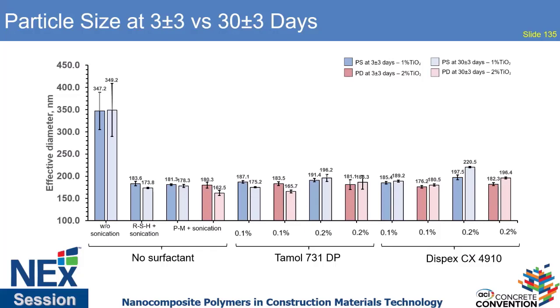However, what is the benefit of using a nano powder titanium dioxide if you have a 350 nanometer particle size, when the bulk material of titanium dioxide is somewhere around there? So you don't get the benefits of the surface area and the surface energy of the material.